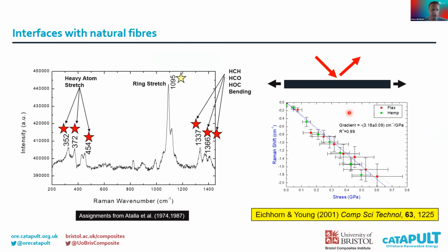Now, we've been working on natural fibres for some time. I only put these two slides up just to point out that we did quite a lot of work in the early days trying to map stresses, using a technique called Raman spectroscopy to map the local stress state inside natural fibres. And I bring this up because I see some of this work might be useful for doing in situ mapping of blade materials possibly.